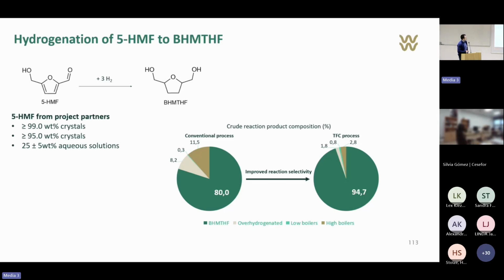And you see that if you just use a conventional hydrogenation process, the selectivity is only about 80%, whereas if we do it in our optimized process, we get a selectivity of about 95%, which is quite a significant increase.